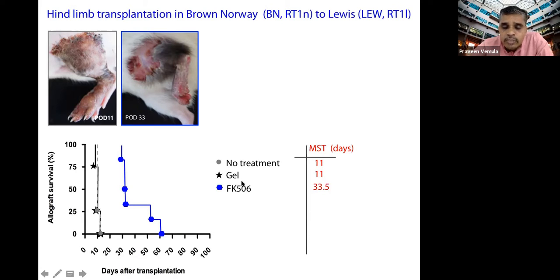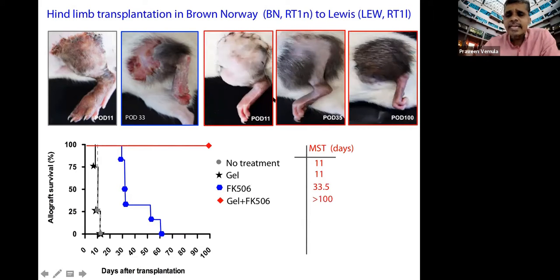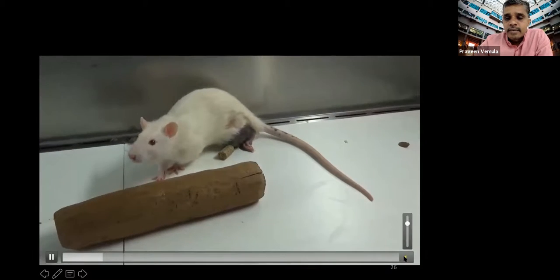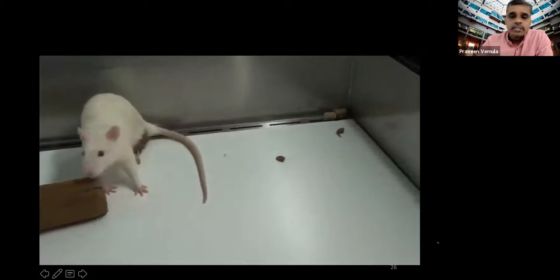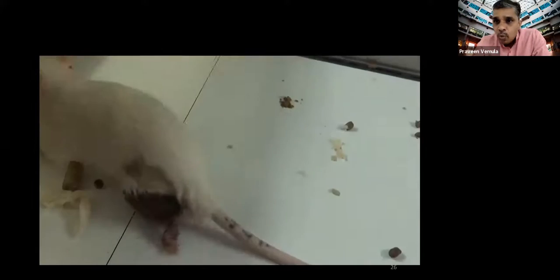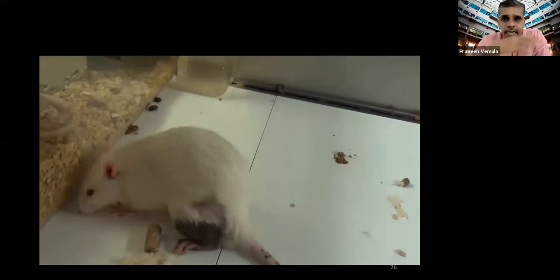Now, the same amount of drug you take and encapsulate in the gel and give as one single injection post surgery. In that case, you can see no sign of inflammation at all, and hair grows back normally, and even after 100 days, we don't see even a single animal reject the graft. And not only that, this animal starts gaining function, and now it is able to move its limbs and so on. And then we have tested their entire systemic inflammation, and the immune system is active.